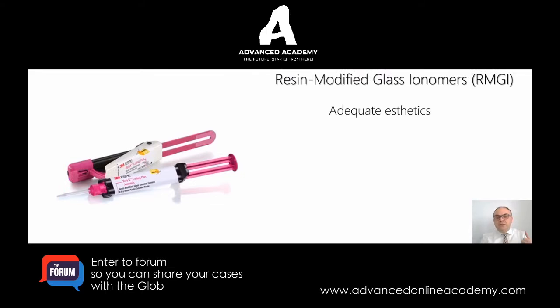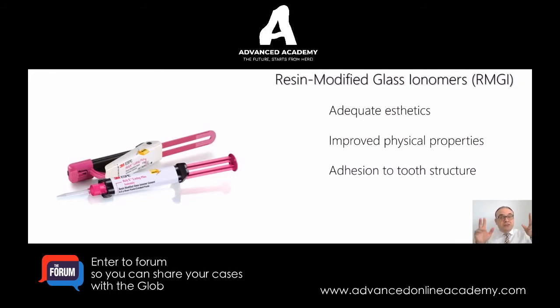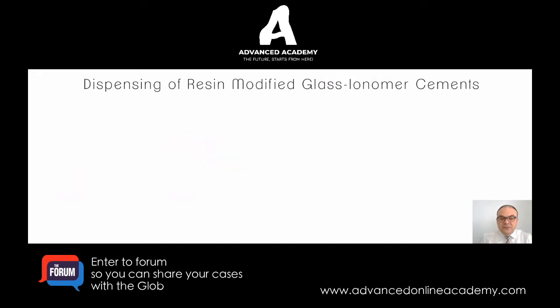Resin-modified glass ionomers have adequate aesthetics and improved physical properties compared to the conventional glass ionomers. They do have proper adhesion to the tooth structure, because I said there is a true adhesion to the dentin. They have improved handling, and fluoride release is advertised heavily by manufacturers, but has very minimal effect after it's been cemented for a few days.